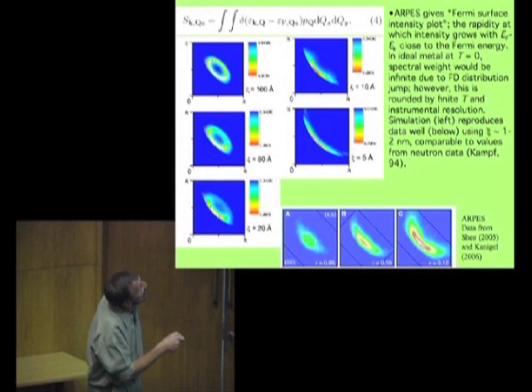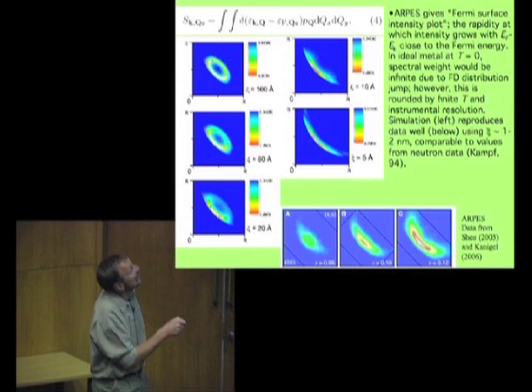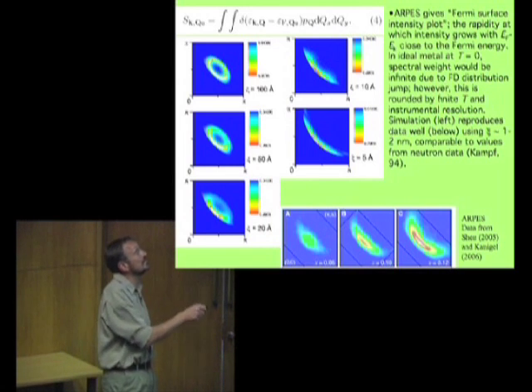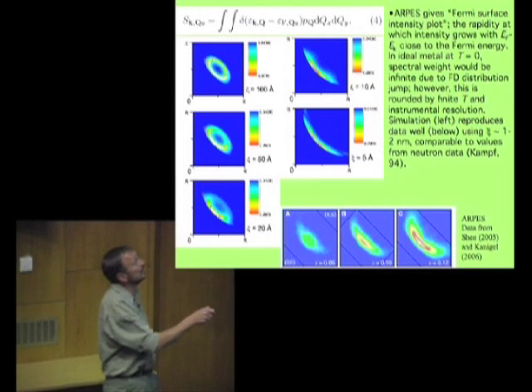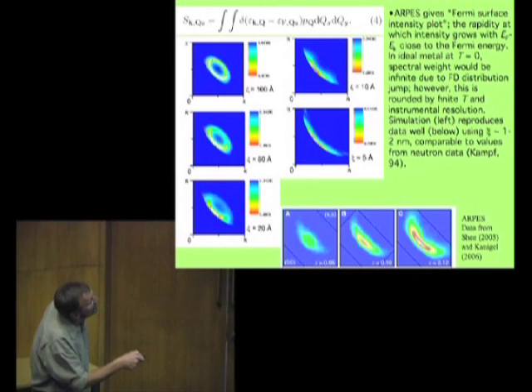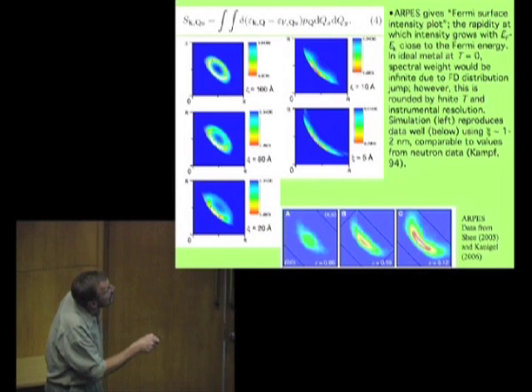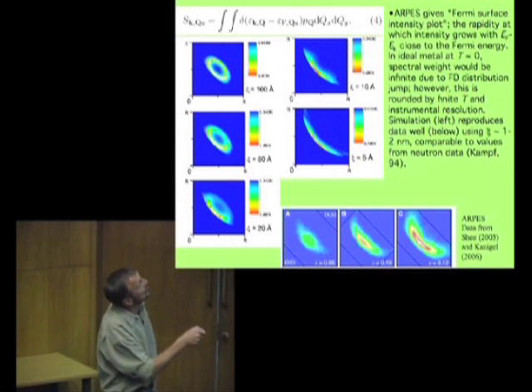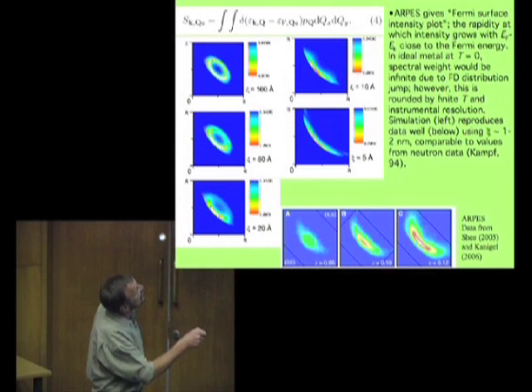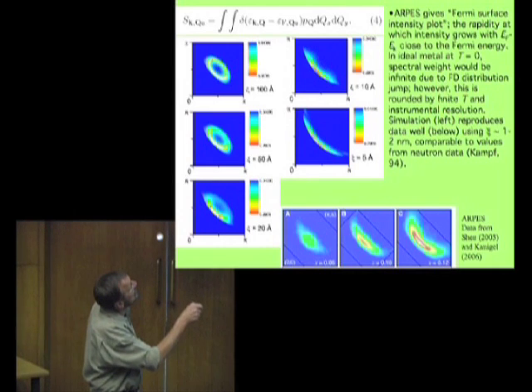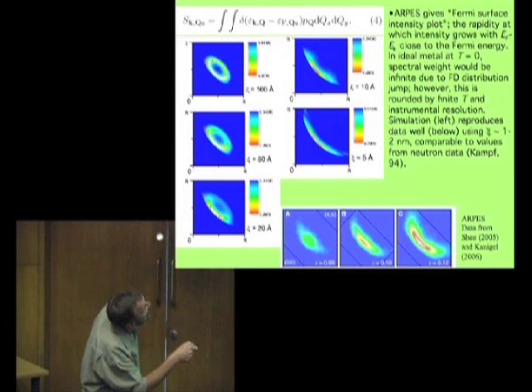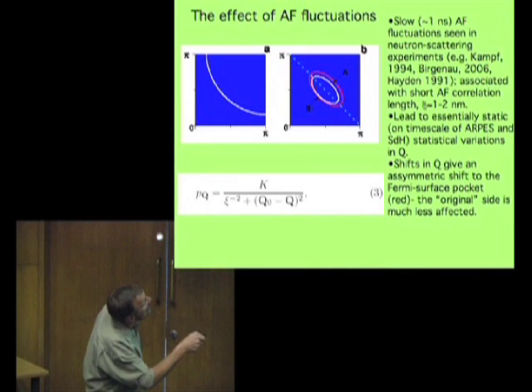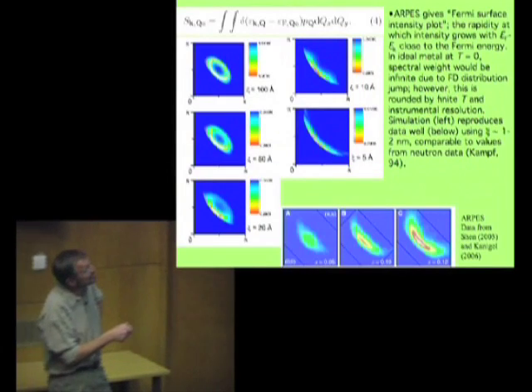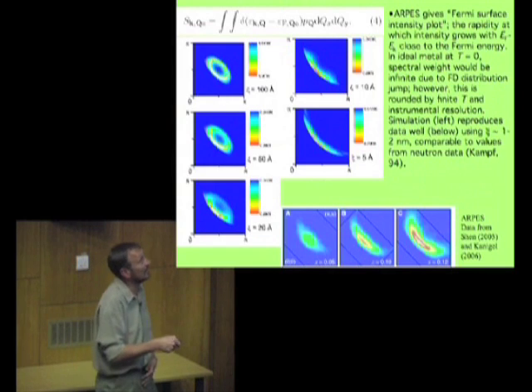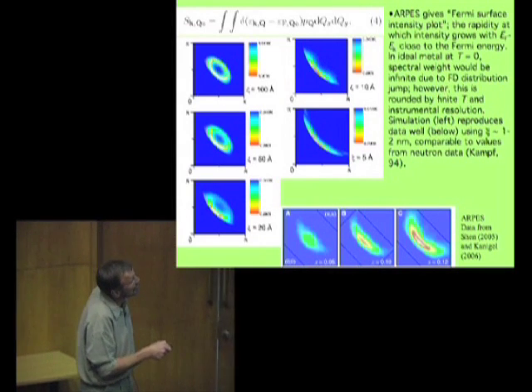As we start to reduce the correlation length, the side of the Fermi surface that's created by reflecting in the new periodicity produced by the antiferromagnetism starts to go all blurry. As you reduce the correlation length further to 20 angstroms, we get this side being almost completely wiped out, and as we reduce it further to 10 angstroms, then all you see is the original piece of band structure that gave rise to the first side of the Fermi surface. So in other words, the statistical variations are wiping out this bit that's caused by reflection and leaving this bit here.